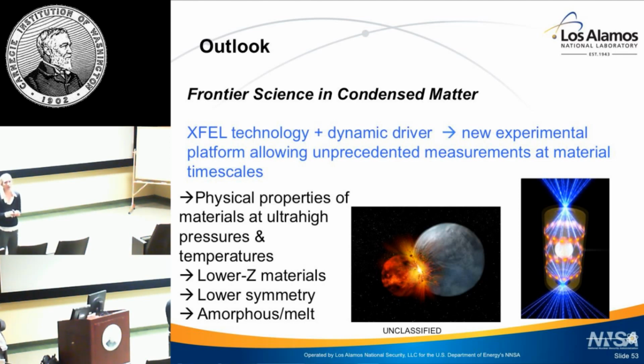When I say fairly well, the uncertainty on the pressure I showed today for SiO2, 33 plus or minus 5, not so good, right? So in that plus or minus 5, which is pretty big, I'm encapsulating some of that gradient, okay? That was for a material that's maybe 100 microns thick, so fairly thick. For some of the thinner materials, we can actually diagnose the pressure state a little better, hinging more on the velocimetry side, transit time, but there is a distribution, you're right.